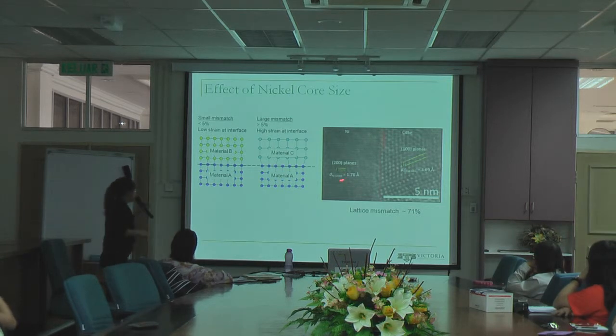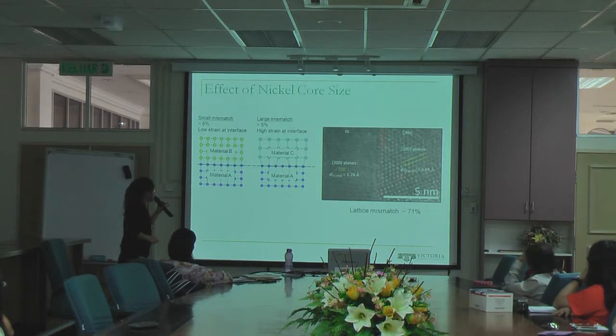And when that happens, a lot of strain arises at the interface. If we look at this example, we have nickel on the left and cadmium selenide on the right-hand side. In this case, the estimated lattice mismatch is about 71%. With such a high mismatch between these two materials, we can imagine that the formation of the interface is probably not very favorable.